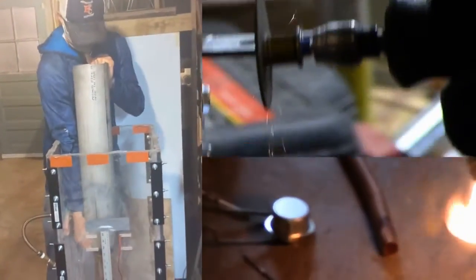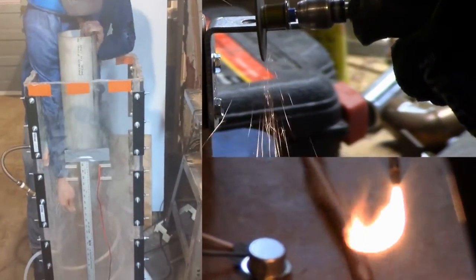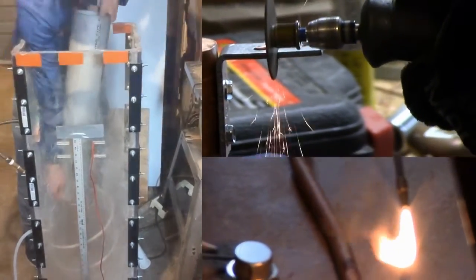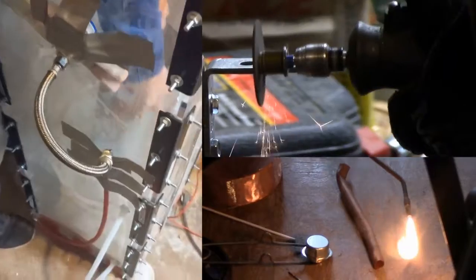All of this rested inside the steel pipe. We were very careful to fill the gap between the outer copper pipe and steel pipe with sand, as if it had been drilled into the ground. Thermal paste was used to ensure full heat transfer on all joints.